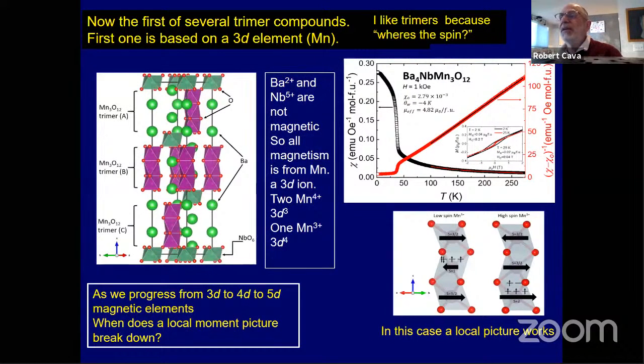So if you start with this thing as a dimer, a magnetic dimer, and they share faces, you can imagine by the Pauli exclusion principle that you're going to get anti-ferromagnetism here as often as possible because these metals are too close. But once you make 3 of them, then this starts to get more interesting. It starts to look to me more like a molecule in a metal. And now this thing can be interesting.